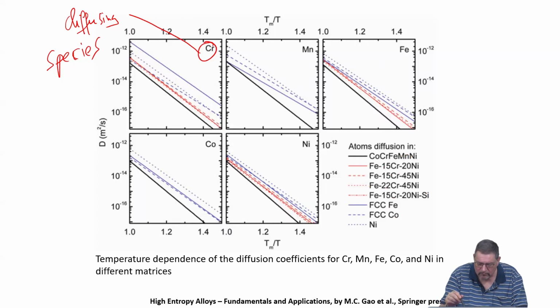So we have self-diffusion of nickel in nickel, and we have impurity diffusion of cobalt in nickel, and so on. Here, how do you measure nickel diffusion in nickel? Only by tracer diffusion, right? So in one plot, interdiffusion and tracer diffusion results are compared. This is very complicated, or actually, in the way it is done here, not correct.